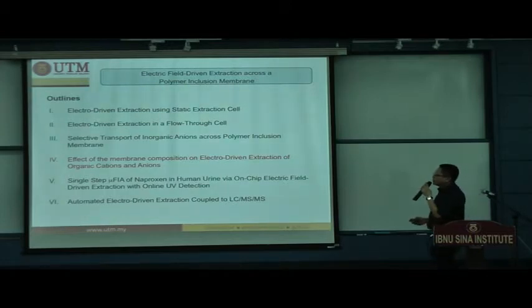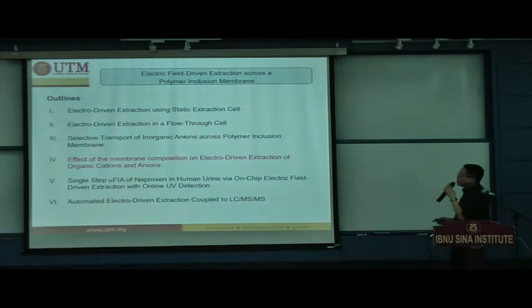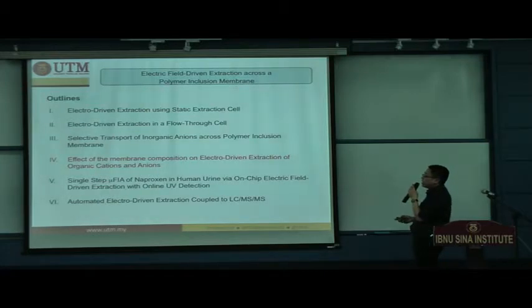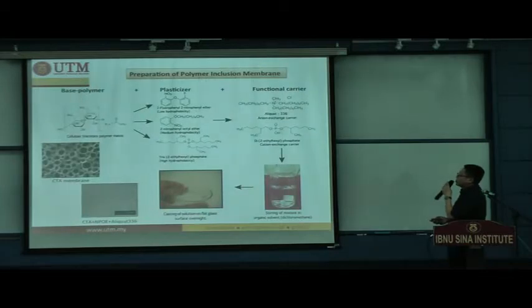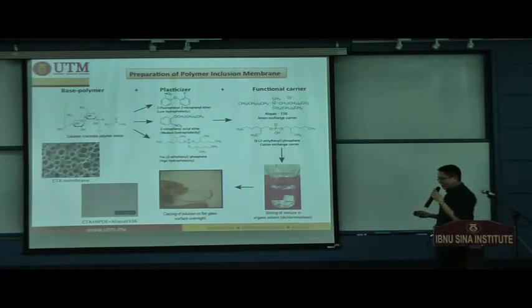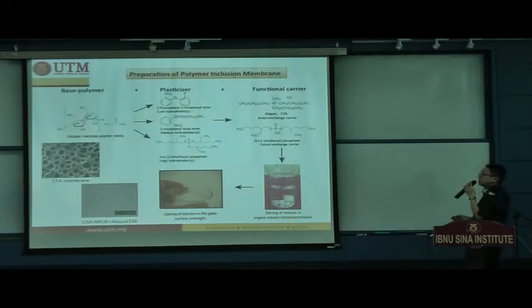And then I would like to show you some fundamental study on the membrane compositions, how, by changing the membrane composition, you are able to affect the migration mechanism of the organic cations and anions across the membrane. So we're back to the diagrams. For this one, it's always consistent, so there's nothing we can do. But for the plasticizer, if you look through the ion-selective electrode research, there are a series of maybe more than 50 kinds of plasticizers that you can use. So this becomes our main interest. The carrier basically just helps you to transport the ion. So our focus will be on the effect of the plasticizer at the present stage.